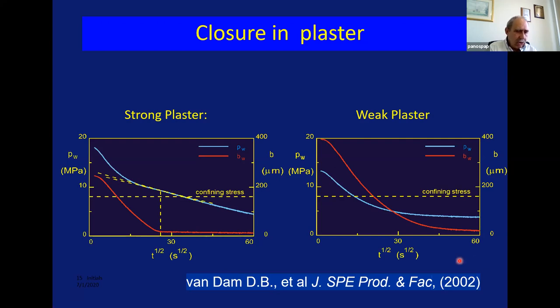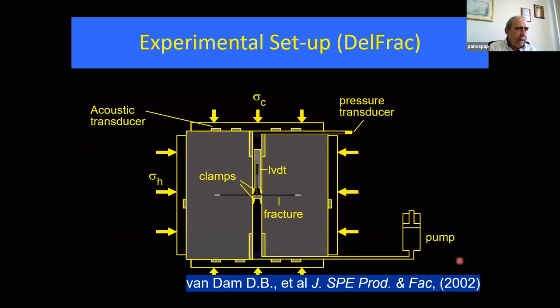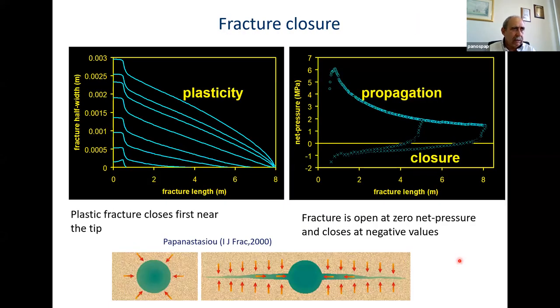The other thing which I forgot to mention, so allow me to go back a little bit here, when the fracture closes first near the tip, the proppant near the tip will be under higher stress. And then it is a matter of equilibrium. The proppant back at the elbow will be under lower stress. So we need to be very careful with the closure stress on the proppant.